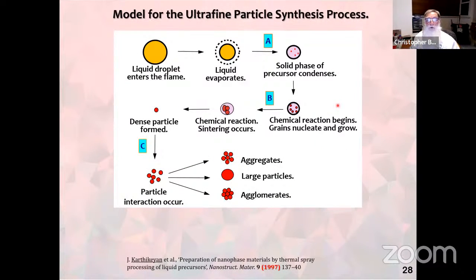So we come up with a model which has been used by many people. This is a model, I emphasise. Not all aspects of it have been proven to be true or correct. But there are 3 steps, A, B, and C, where the liquid droplet forms solid phase of precursor condensates. We may get dense particles formed, and we may get aggregates, large particles, or agglomerates.